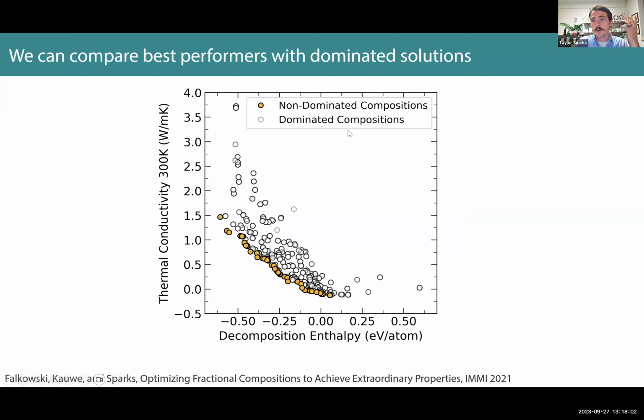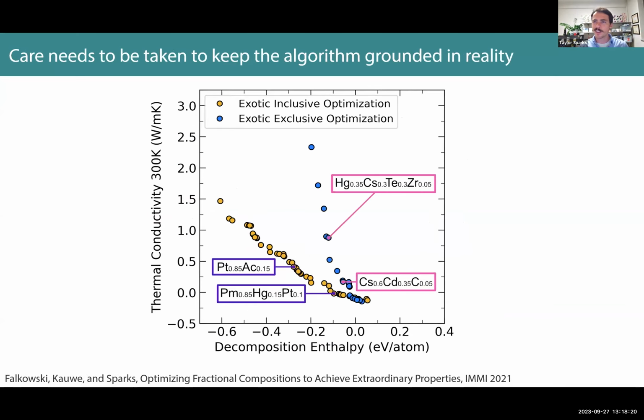What you see here is a Pareto front plot where you see two parameters. We were trying to minimize thermal conductivity, minimize decomposition enthalpy. So give me stable materials that don't conduct heat. And the materials shown in yellow are what are called your non-dominated compositions, sometimes called the Pareto front. These are essentially your best materials that exhibit a trade-off between these two parameters. But when we actually looked at the chemistries of those materials, they were pretty crazy. The genetic algorithm, without some sort of guidelines, would produce nonsensical structures. So we had to clean it up and throw out things that didn't make sense. And then the stuff that was left over actually looked pretty compelling.